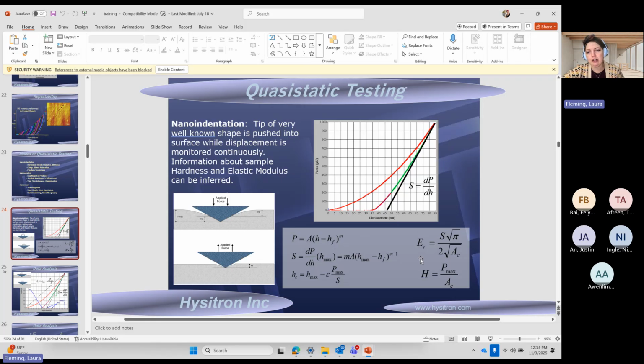at length. But what I want to note here is that the reduced modulus is dependent upon the stiffness, which we measure from the graph. Calculate from the graph would be the better way of putting that. You know, pi over 2 and a square root of the contact area. Again, we're going to talk about that in depth. The hardness is dependent upon the maximum force, which we measure directly from the transducer. And again, the contact area.